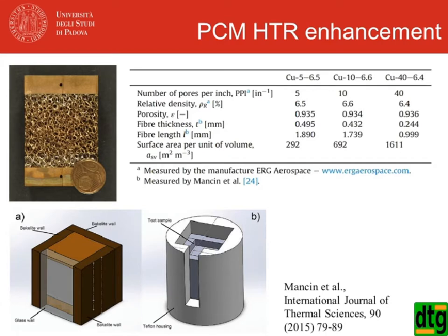So the initial idea was to study this system in a very simple setup. We had these samples which were 40 by 40 by 40 millimeters, and we covered those samples with bakelite walls and one glass wall to observe the phase change, and then we inserted that in the Teflon housing, as you can see here, with a window to follow the phase change process. So basically, this is a module. All the surfaces, all the walls were adiabatic. Okay, so we can imagine it as a single element of a bigger system.